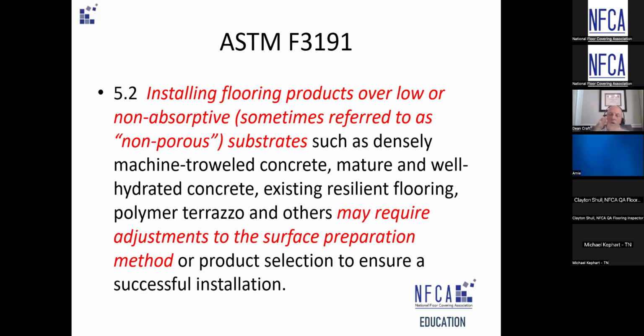Keep in mind, another thing I want to point out is just because a surface is non-porous on a concrete does not mean that surface is contaminated. I've heard a lot of people say, "Oh, it means there's a curing compound. We got to strip it off." No, it probably means the concrete was troweled. And in fact, most concrete will test as non-porous because of how it's finished. Those riding machines out there put a lot of weight and pressure. And if you look at ACI, the purpose of troweling is to provide a smooth, dense, hard surface, which means non-absorptive.